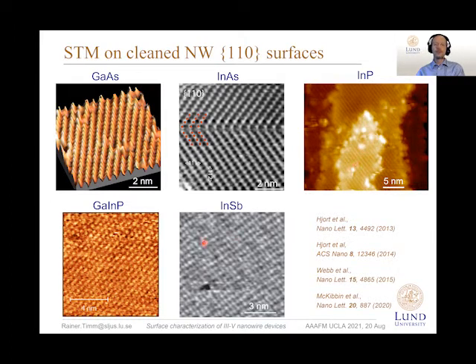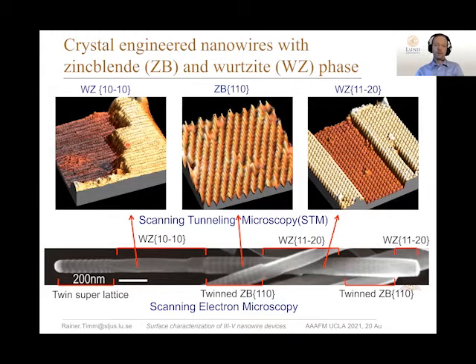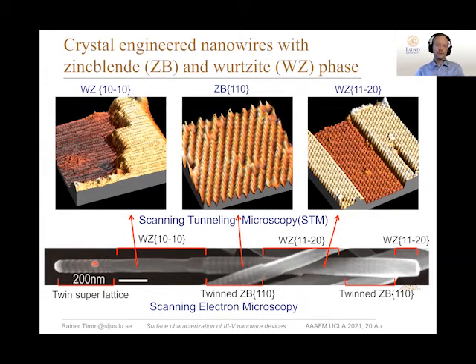More exciting than these homogeneous surfaces are heterostructures, and one very specific heterostructure for III-V semiconductor nanowires is the different crystal phase. Usually these III-V semiconductors grow in a cubic zinc blende phase, but only in these nanowires they can grow either in zinc blende or in a hexagonal wurtzite phase. Growth experts nowadays can tune this and grow tailored nanowires with zinc blende, wurtzite, zinc blende, wurtzite, zinc blende areas and so on.